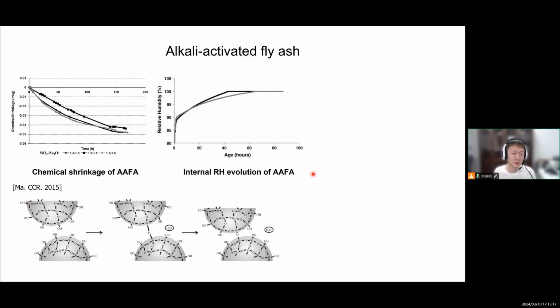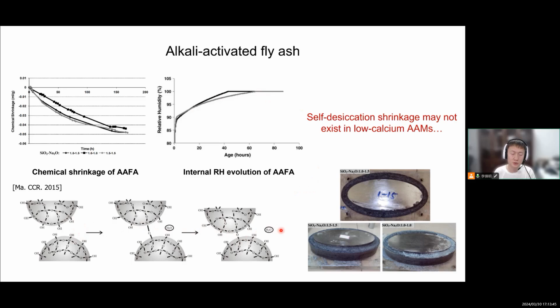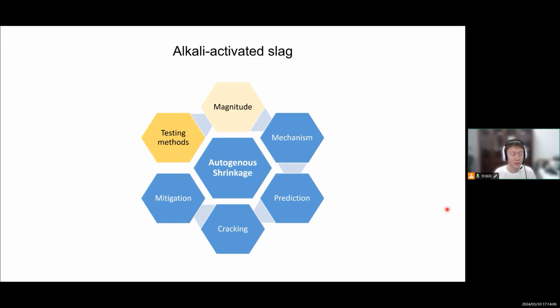And then what is the mechanism? Then we hypothesize maybe it's due to syneresis. Syneresis means the reaction uses the water, so the water is hydrolyzed first. They use the water, but then during or after the polymerization, the water returned to water molecules, which means the water is not really used by the reactions. So the self-desiccation shrinkage may not really exist in low calcium AAMs. Consider this, and also the low cracking potential caused by a sealed condition. This is experimentally done by Dr. Yufei Ma. Because of this, I didn't really go further because I think the autogenous shrinkage is not really a big problem for these low calcium AAMs. Then I spent more time on alkali-activated slag.